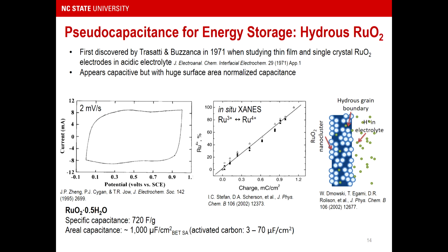You have these ruthenium oxide nanoclusters that are electronically conductive, connected to each other, and separated by hydrous grain boundaries that were providing exceptionally fast proton transport. And this was really the first time that the idea of pseudocapacitance was extended from that adsorption-desorption understanding in the 1960s to something that could now be utilized for energy storage devices.